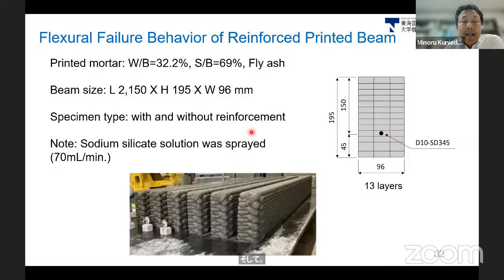And I will show you the third topic, on the flexure failure behavior of reinforced printed beams. We made the beam specimens using the 3D printer. The printed mortar has a water to binder ratio of 32.2%, and an additive with fly ash has been used for the mix. The beam size is a length of 2,150, a height of 195, and a width of 96 millimeter. And the specimens were with reinforcement and without reinforcement.